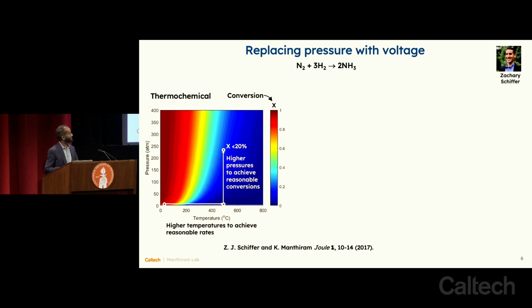Now, the way we solve that is by pressurizing. Because this is a reaction in which we have a reduction in the number of moles, pressurizing by Le Chatelier's principle allows us to shift the equilibrium of this reaction to the right. And so if we go up in pressure to 200 to 250 bar, we can now get to an ever so slightly lighter shade of blue here, where we have about a 15% single pass conversion. And this is actually how we make all the world's ammonia today, with a 15% single pass conversion.